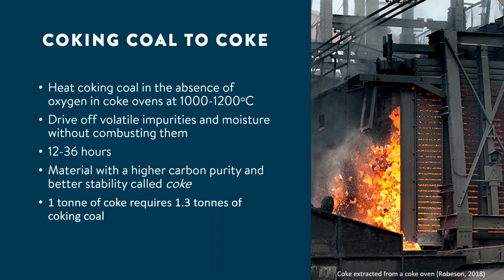Now, mineral matter can be a problem in coking coal. An internationally traded coking coal should be less than 10% ash because a rise in ash content effectively requires more coal throughput per ton of coke, requiring more energy and increasing the need for maintenance in the coke ovens. Steelmakers are always keen to find alternatives to coke to reduce costs, but also to prolong the life of their coke ovens. Few alternatives exist that can replace coking coal in terms of quality, abundance, and cost. But as a general rule, 1 ton of coke requires 1.3 tons of coking coal.